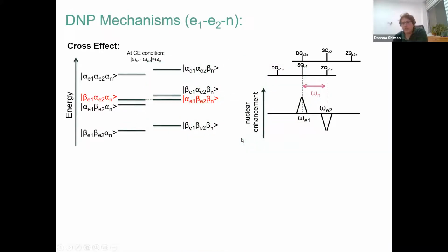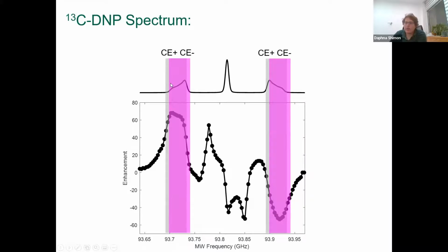But I also mentioned the cross effect, and so for the cross effect, in order to see where we expect it, we need to think about two electrons and a nucleus, and if the two electrons are dipolar coupled and the frequency difference between the two electrons exactly matches the nuclear Larmor frequency, then when we irradiate on one of the electrons, we get positive enhancement. And when we irradiate on the other electron, we get negative enhancement. And so we expect enhancement separated by omega n. So if we look at the two outer lines, these are the only lines where there's two electrons that could fulfill the cross effect condition. What we then see is that it doesn't seem like there's very much of it right here, because we would expect a positive and a negative with a large overlap, and that doesn't seem to match the shape.